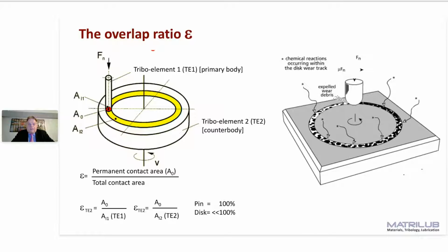And what happens is better shown here. You have the contact zone. In the contact zone, the tribofilm or the oxides or whatever may have been worn, they come out of the contact, and in this contact-free time, this can be regenerated, replenished, and it is logical. When you now increase the speed, you may come into a situation where you wear more of this tribofilm than it can rebuild. And this also explains why often you have an impact of the sliding speed on test results. At a certain point, you have a low wear, high wear transition.